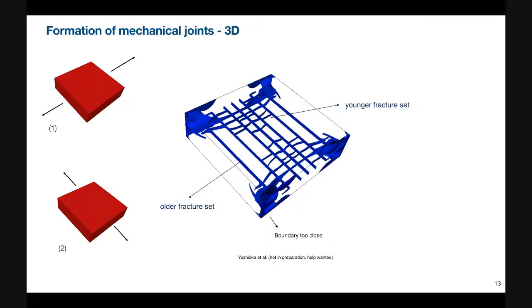So okay, this boundary, please ignore this weird looking fracture. The boundary was too close. But these big fractures are the fractures created by the first episode, and we can consider them as an older fracture set. And then these shorter fractures were created in this loading, and they are considered to be a younger set of fractures. And you notice that the younger fracture sets tend to be terminated by the older fracture set. And this is consistent with the field observation.